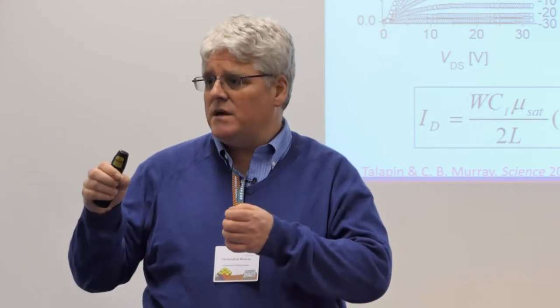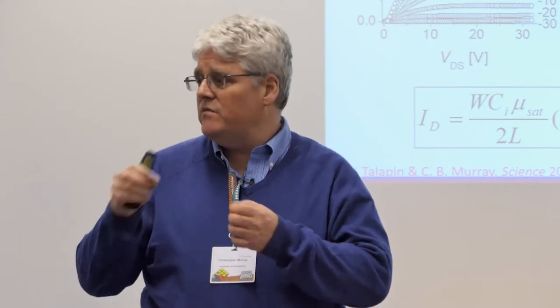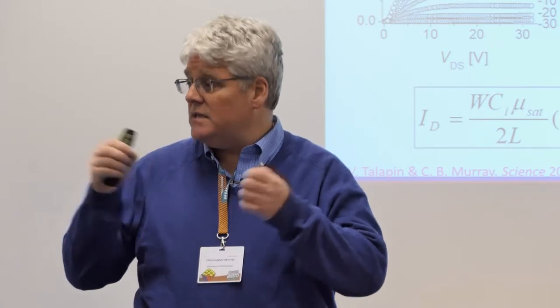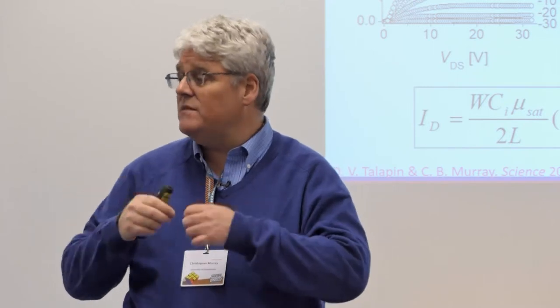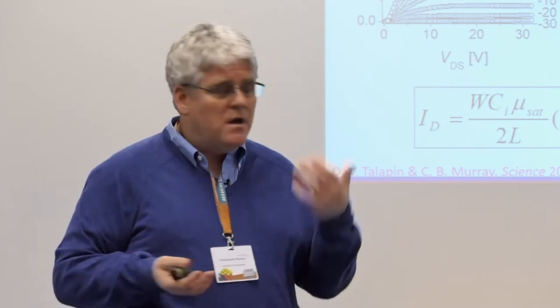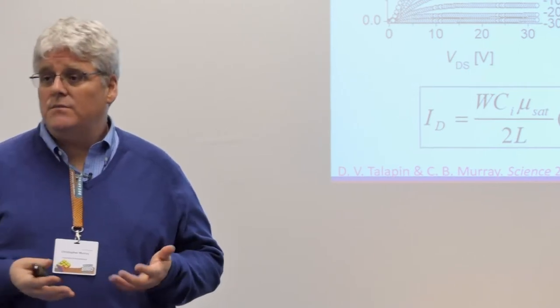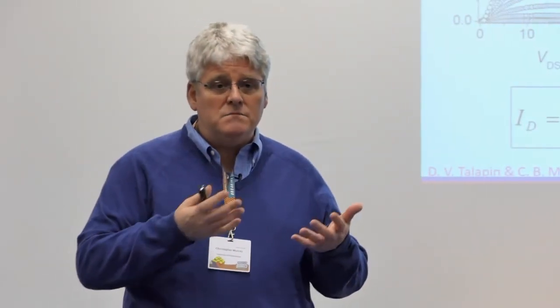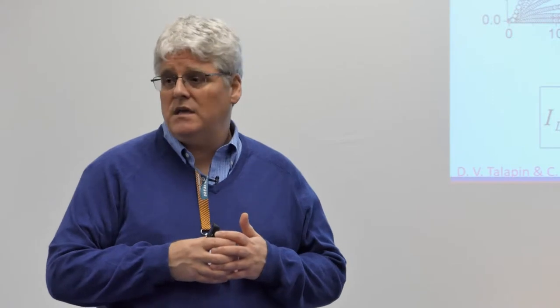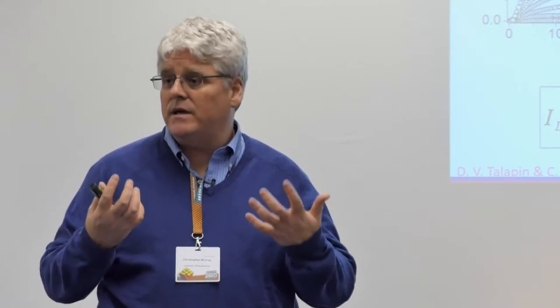If you move a little bit above 1 in mobility, that means that the scattering is not happening at every jump, but there's an argument that you're moving into a regime in which you get some extended transport, or potentially as you go higher in mobilities, maybe even the development of a new band structure. So for us, this was kind of the tipping point. It was the opportunity to begin to move into a regime where you could think about charge delocalization in these materials that was more akin to the band model or band development that we think of in